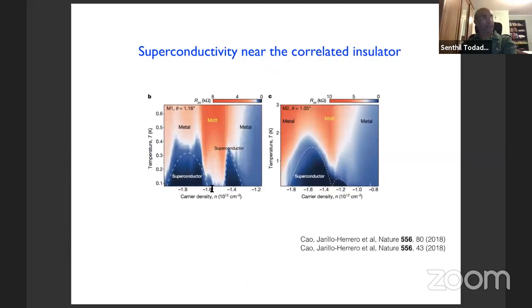Now, because this system can be easily tuned with gate voltages, Pablo's group, Pablo and his students, they managed to dope away from this correlated insulator. So they called it a Mott insulator in their original paper. We'll get back to this. But this insulator at partial band filling, when you dope slightly away, they discovered that you get a superconductor. Okay, so in this original data, the maximum TC is about 1 Kelvin. So these days, people make devices in which the TC is on the order of maybe up to 3 Kelvin or so. Okay, so you see a correlated insulator, and you see superconductivity in the vicinity of that correlated insulator.